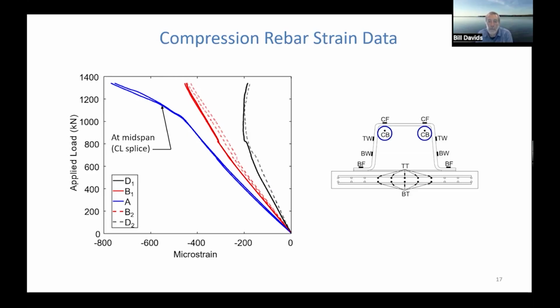That means there's significant compression in that concrete infill. And it's increasing as we move along the splice. And that's consistent with that shear stress transfer of the compression stress in the carbon fiber bottom flange or top as tested into the concrete itself. In other words, the load transfer, the stress transfer is happening as we assumed and expected it would.